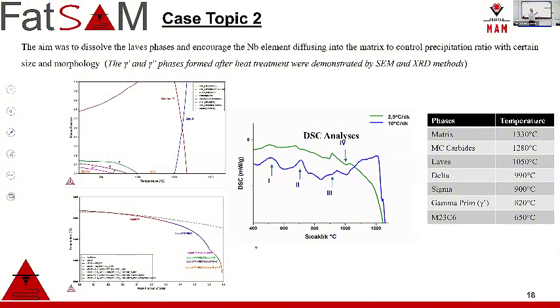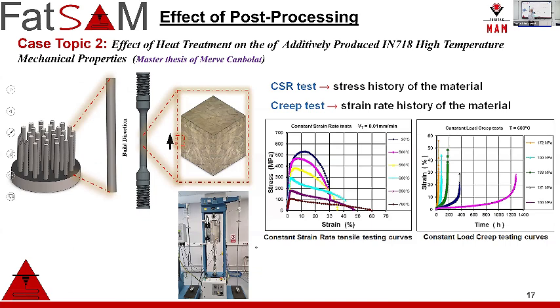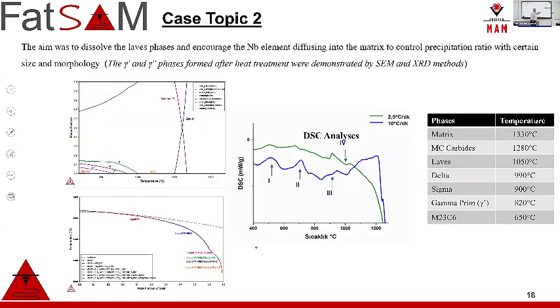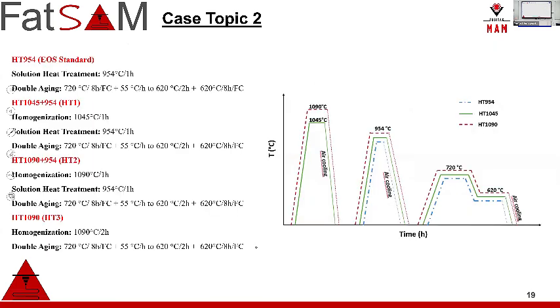The problem in 718, this is a 718 material, as I said before, is the effect of heat treatment, additively produced Inconel 718, Laves and delta phases. Yes, with further heat treatment procedures we can obtain better mechanical properties, but there is a risk of formation, according to the cooling and solidification graphs, of Laves and delta phases, which are undesired intermetallics in the microstructure that decrease the mechanical properties of these materials. In this study, we designed 3 heat treatments and compared them with the standard conditions.